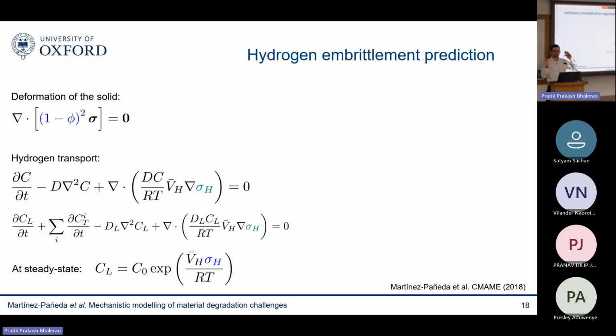If I focus first on the coupling between mechanics and hydrogen transport, I've shown you the simplest equation one could use. In reality, the hydrogen not only travels freely through the crystal lattice, it's also sequestered or trapped at microstructural defects. So you can expand your model and add not only a lattice hydrogen concentration, but also a trapped one. And then how this evolves depends on Oriani, McNabb-Foster. There are a wide range of models that assume either thermodynamics or some sort of kinetics. But again, what I want to emphasize is the coupling with mechanics.